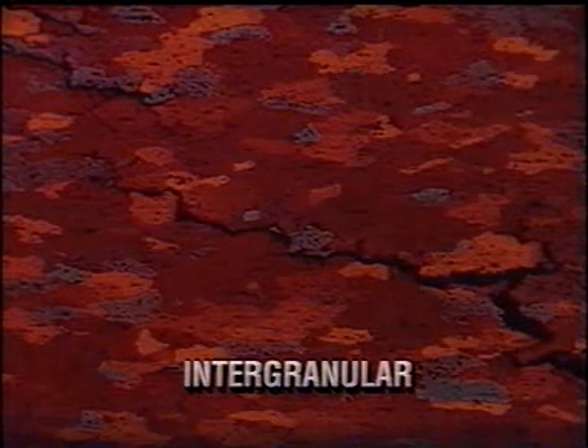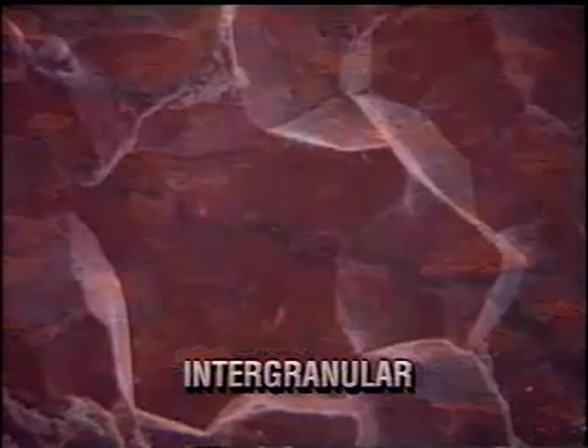The second type of brittle fracture, intergranular, is easy to recognize, but its cause is much more difficult to identify. The surface of an intergranular fracture, most often, initially appears bright and sparkling. It is characterized by a rock candy appearance, easy to recognize in electron microscope examination. The cause of an intergranular fracture is difficult to recognize because the complexity is promoted by the cumulative effect of environmental factors and sustained stress, by grain boundary embrittlement, and by impact loading.